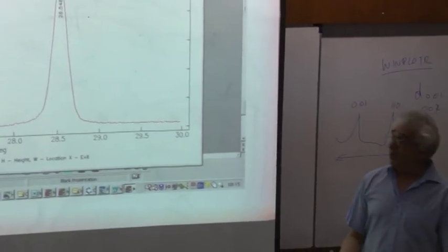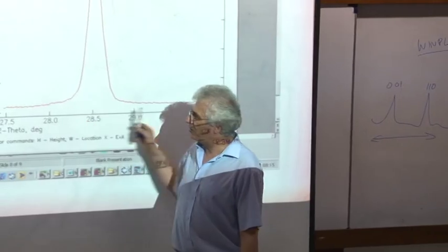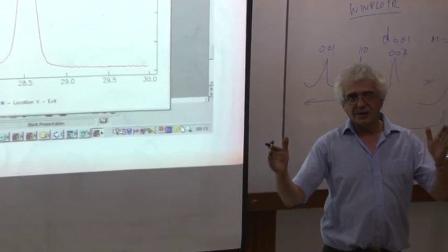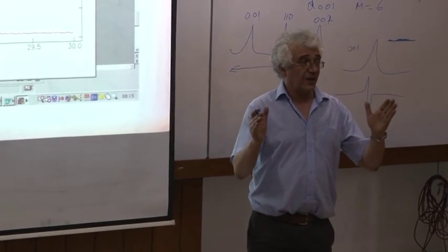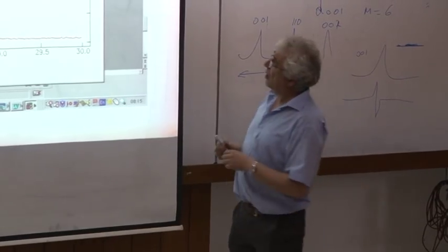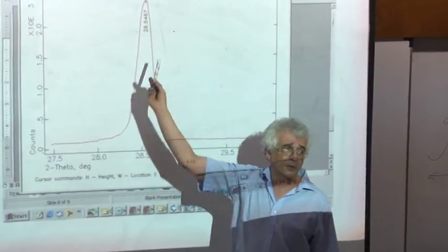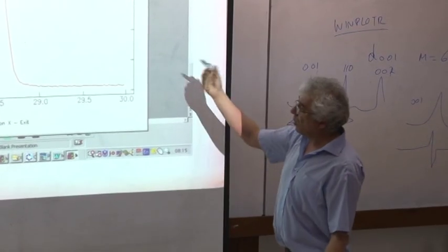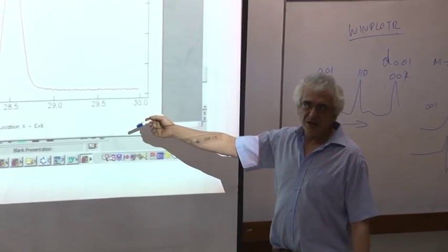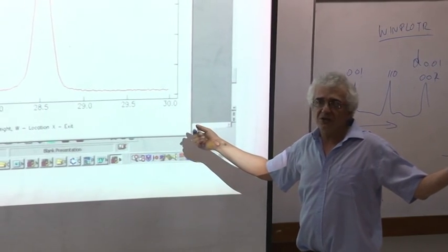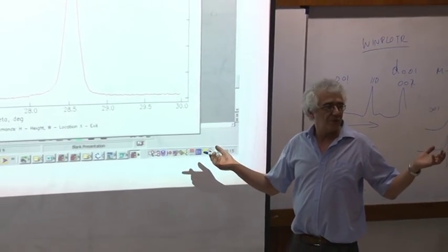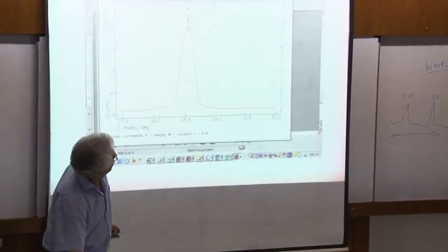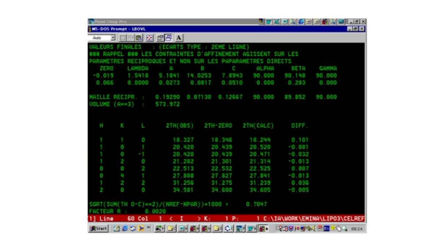And if you're going to measure it by hand, make sure you focus in on the peak. Remember that you are limited by the resolution of the screen of your computer, and so it tries to compromise for that. So sometimes you may get a fairly inaccurate reading for the center of your peak, unless you've blown it up to the maximum. So always do that. You don't need so many peaks. Depending on how many parameters, you can do a dozen peaks for a normal structure, but you can do it on 6, depending on how many parameters you want.